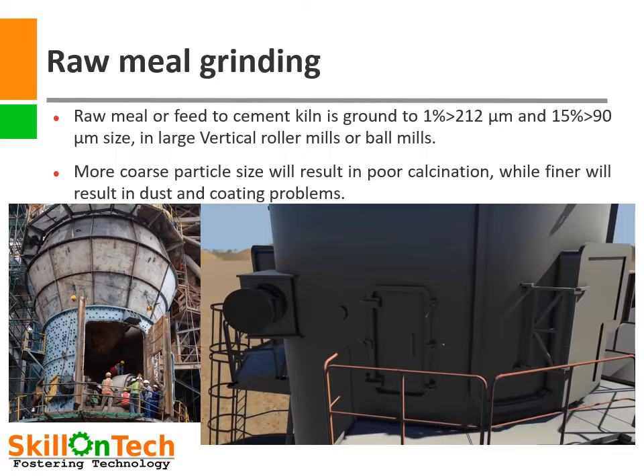This homogenized mineral is transported from stockpiles to separate grinding bins such as low grade limestone, high grade limestone, iron oxide, etc. Carefully mixed feed from these hoppers is fed to vertical roller mills, or VRMs, for further grinding. In some old plants, ball mills are used for the same purpose. The product of the VRMs is expected to be 1% residue on a 212 micron sieve and 15% residue on a 90 micron sieve. More coarse particle size will result in poor calcination, while finer particle size will result in more dust circulation and coating problems.